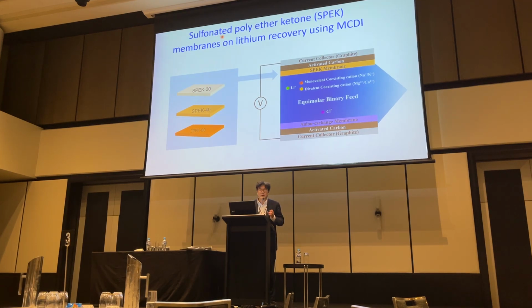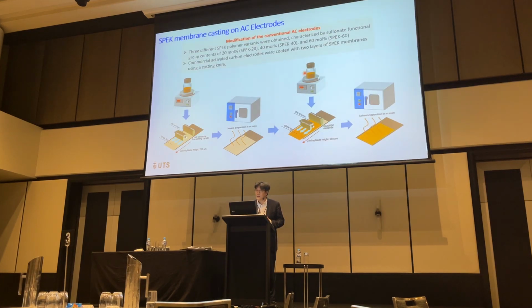The sulfonate group attaches with your lithium, so that you can capture more through the ion exchange function, and you will have a higher concentration of sulfonate functional group, which will have more lithium combination. Which means you will get more selectivity of the lithium when you have SPEEK 20%, 40%, 60%. Also, when you have more sulfonate functional group, you have more hydrophilicity. So we changed the cation exchange membrane, and then looked at the selectivity of our lithium recovery.